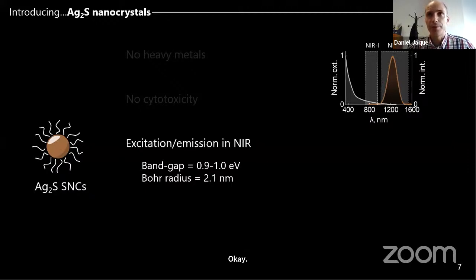Okay, the emission is in the infrared. When you measure the emission of these semiconductor nanocrystals, this is the emission band. This is a very broad band with a maximum around 1.2 microns, that is just in the middle of the second biological window. It means that the luminescence generated by these nanoparticles will propagate through the tissues without attenuation.